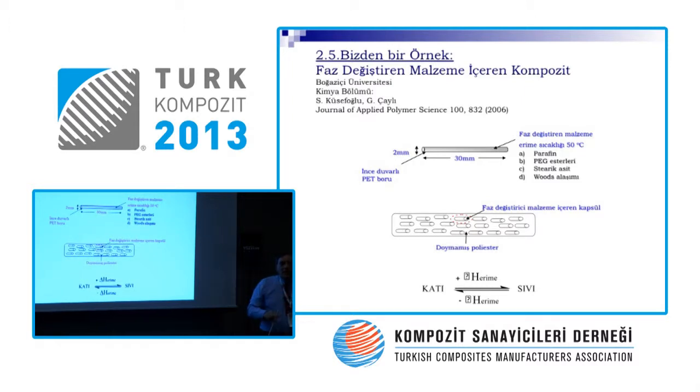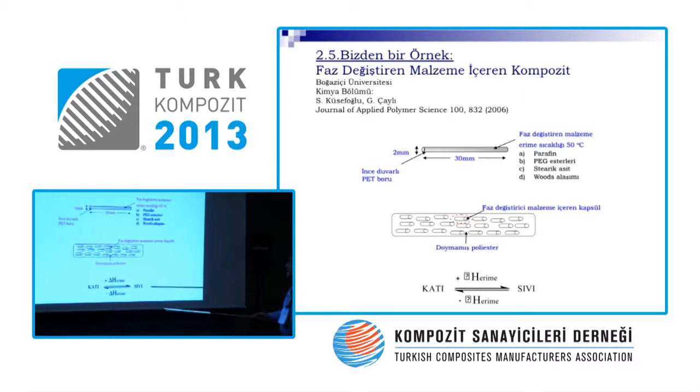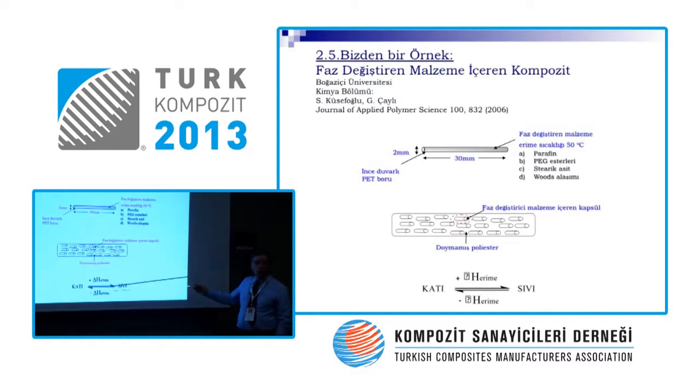We tried plenty of materials, because we want the energy that comes out of melting or solidifying. That is why we are looking for a material with a high enthalpy of melting. The material needs to be as crystalline as possible.